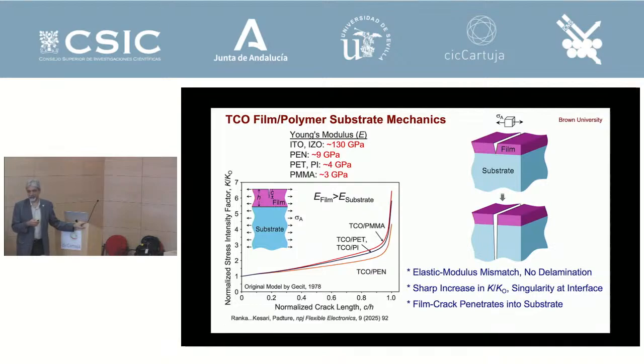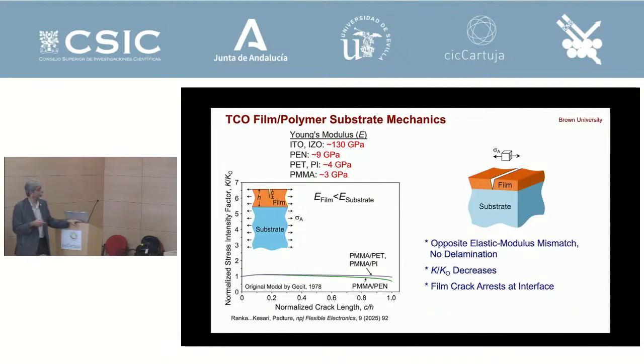And so that gave us a clue. Of course, the TCO is 130 GPa, the polymer is 9 GPa, right? And therefore, that difference is why this cracking occurred, regardless of the toughness of the polymer. And this is driven by these intense shear stresses that occur at the point there.